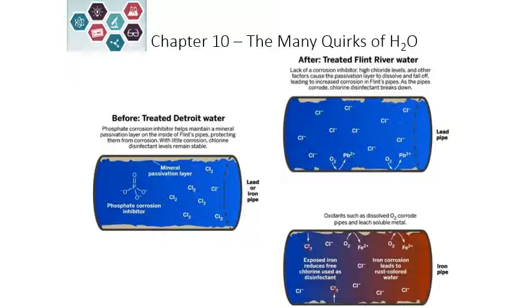When they switched from treated Detroit water to the Flint River water, no corrosion inhibitor was added. The high chlorine levels caused those protective layers inside the pipe to be oxidized, and lead started leaching from the pipes into the water supply, allowing lead to reach people's homes. This was also a problem with iron pipes as well.